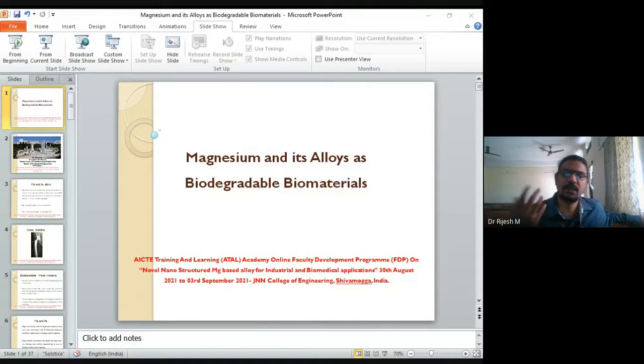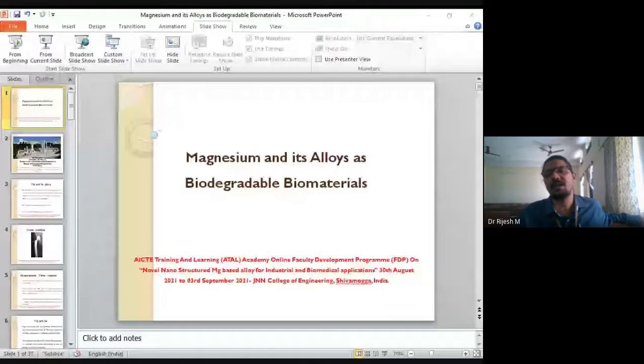But stress shielding is something which is very common when you have this implant. If you look at the stress shielding that happens, magnesium may have a stress shielding which is much less than titanium and stainless steel, because of the difference in the strength of titanium and cortical bone, and magnesium and cortical bone. Magnesium is much closer to that.